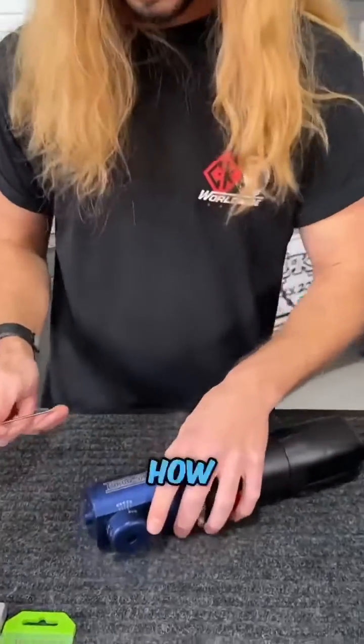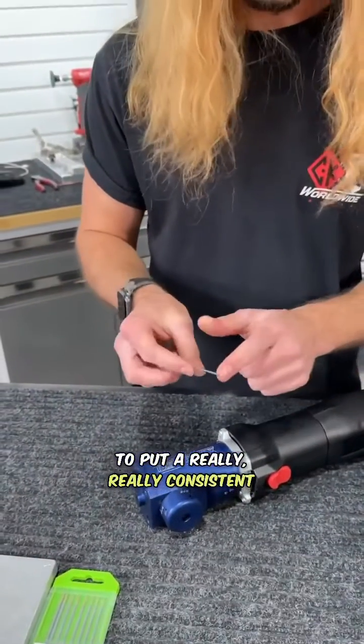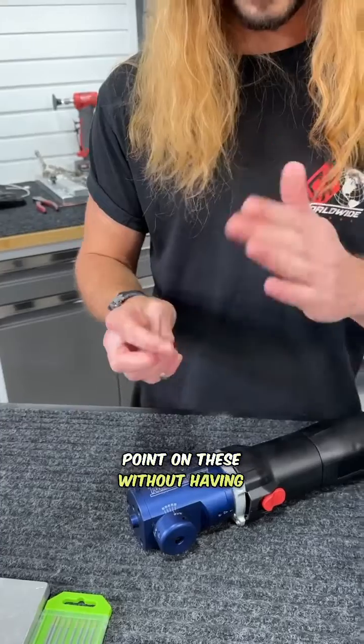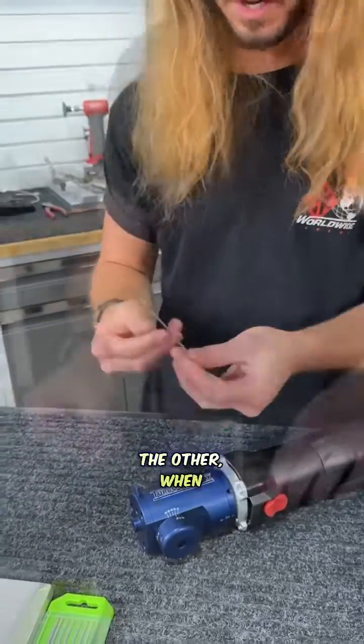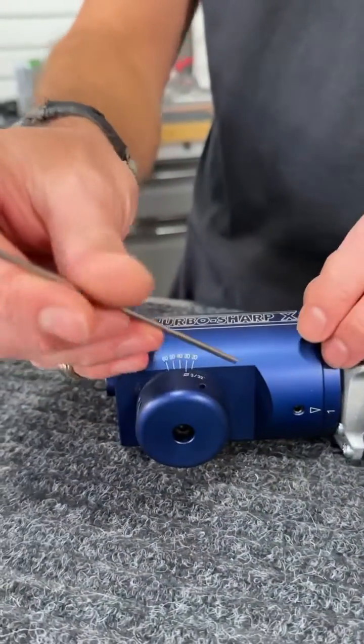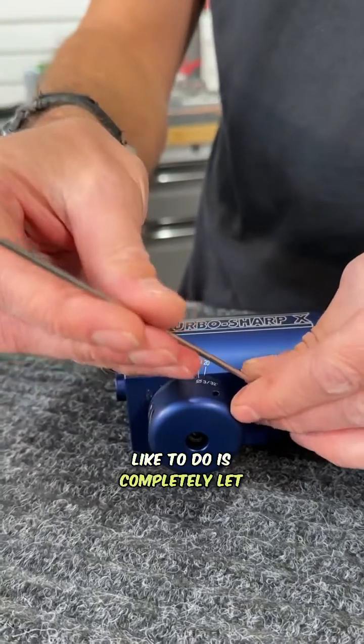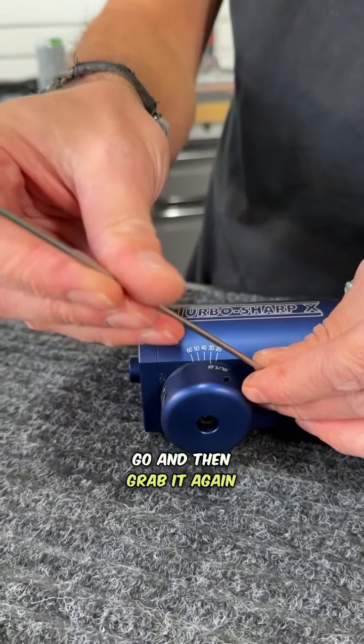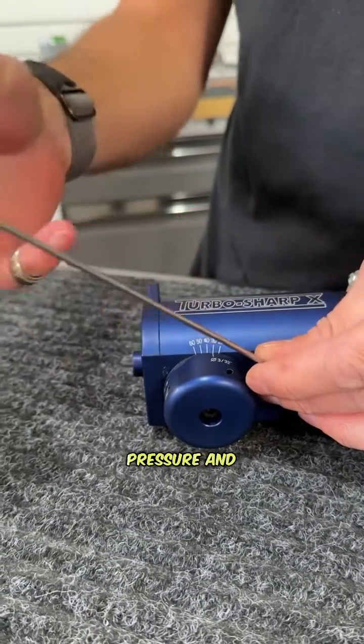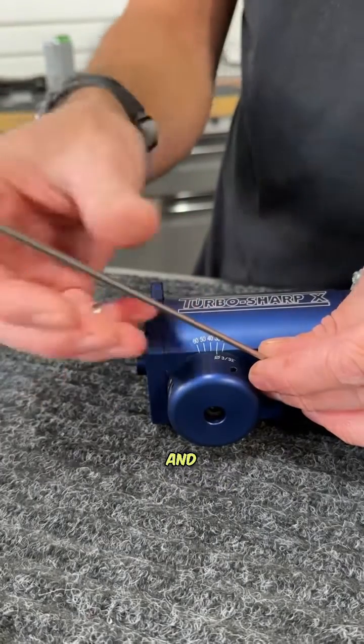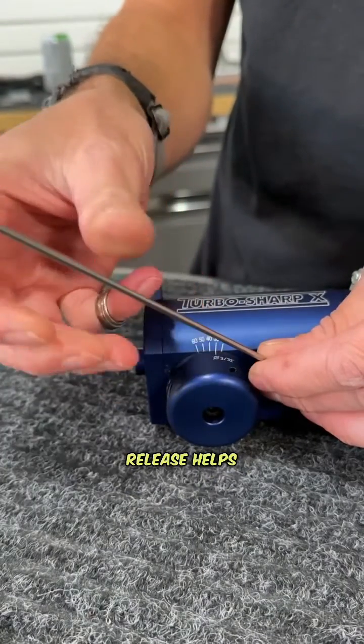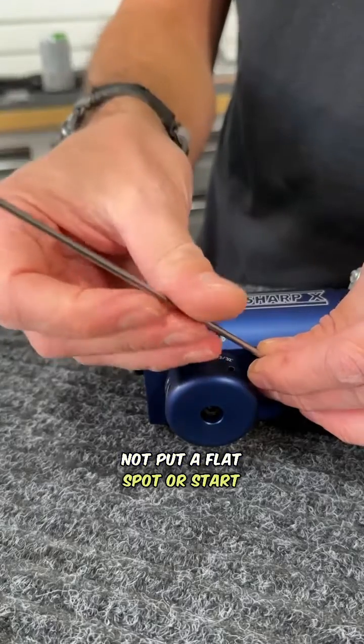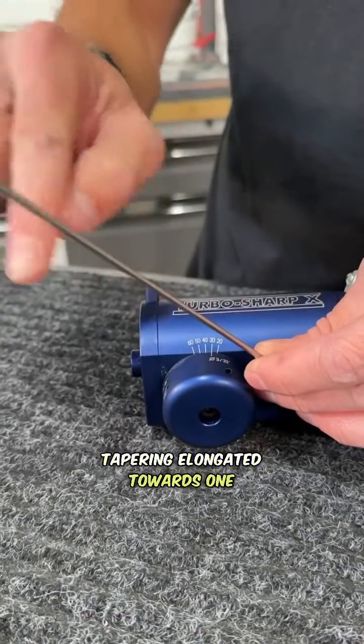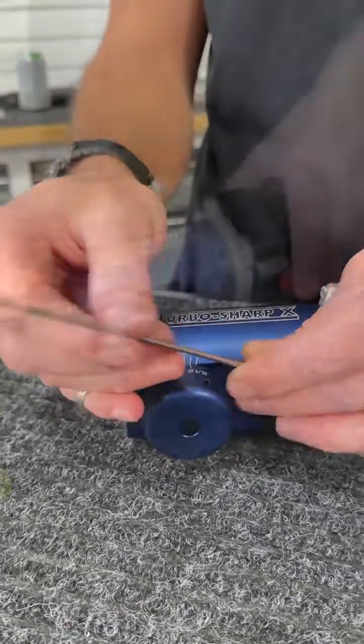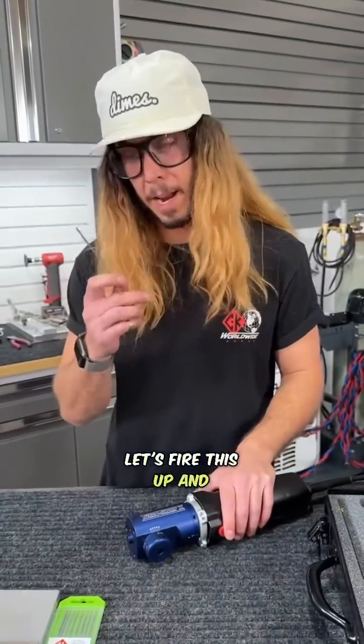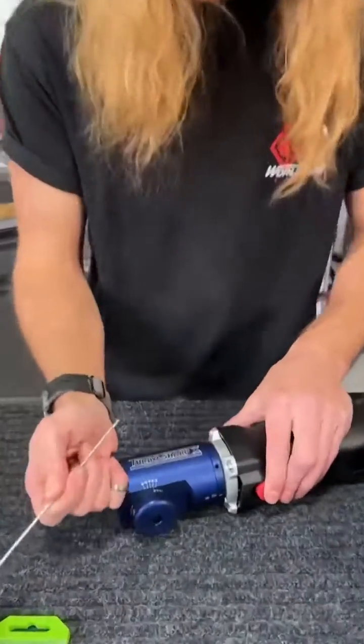So the best way I know how to put a really, really consistent point on these without having it taper to one side or the other, when I put the electrode in the grinder and I spin it, what I like to do is completely let go and then grab it again and put a slight amount of pressure and then let go and spin again. And just that little bit of release helps the electrode not put a flat spot or start tapering elongated towards one side of the electrode or the other. So let's fire this up and sharpen our lasers.